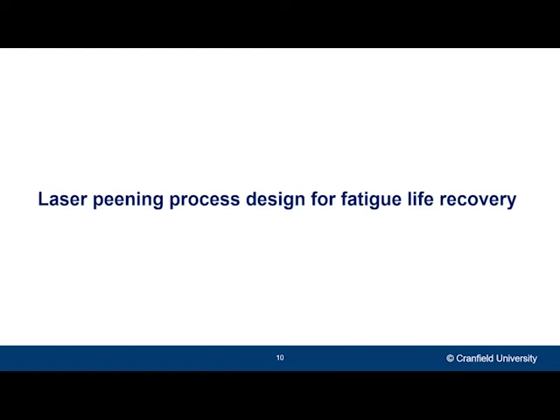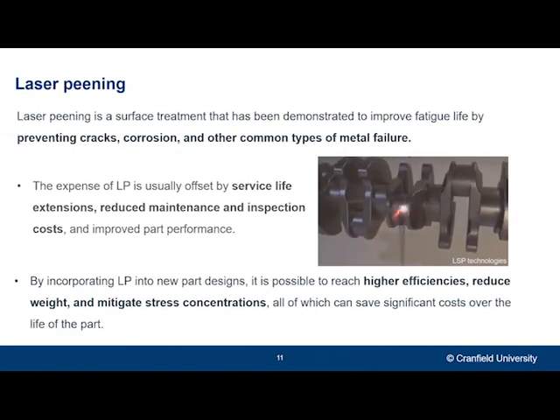So in order to try to improve the life of these joints and prevent crack initiation from this lack of penetration defects that I just showed, the main objective of this project, as I told you in the beginning, is to understand if laser shot peening could have a beneficial effect on this type of joint. So Cranfield University has been involved in other projects where laser peening was used to treat aluminium sheet material, more specifically with scratch damage done to the material. And those results were very promising at the time. So the hypothesis here is that laser peening could potentially have a similar beneficial effect in the friction stir welded aluminium.